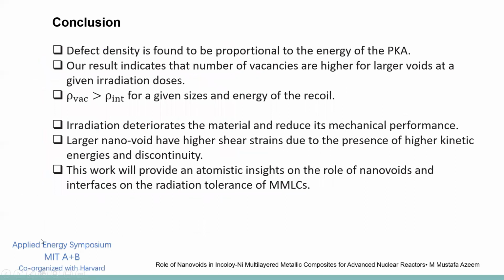Okay, in conclusion, we observed that initially for the displacement cascade, the defect density is proportional to the energy of the incident particles. Also, the number of vacancies is higher for the larger voids. The defect concentration for the vacancy is higher than the interstitial, and the radiation throughout the material affects the mechanical performance. Larger voids have the higher shear strains due to the presence of higher kinetic energies and discontinuity. Our work at the atomic scale provides an understanding of the defective nature of the interfaces containing voids. This is very crucial for developing multi-layer metallic composites for the harsh conditions observed in advanced reactors. This study will serve as a predictive model for developing radiation-resistant models.